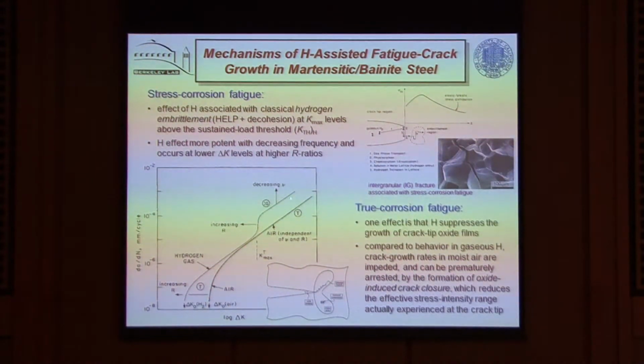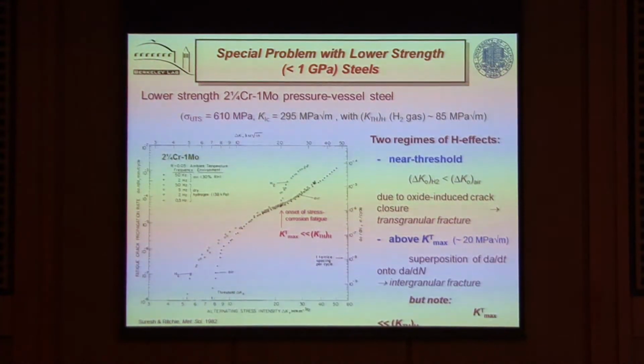There are different mechanisms here, but from the engineering perspective, we need to be able to document how these data change and use this as a prediction of life. Now, there is one final point I want to mention here, is that this approach of superposition has been around some time and works extremely well with high-strength steels. But if we go to a low-strength steel, and low-strength steels are still used in a tremendous amount in engineering because they have higher toughnesses and are less prone to fracture, below about a gigapascal, if we try this approach, it doesn't work.